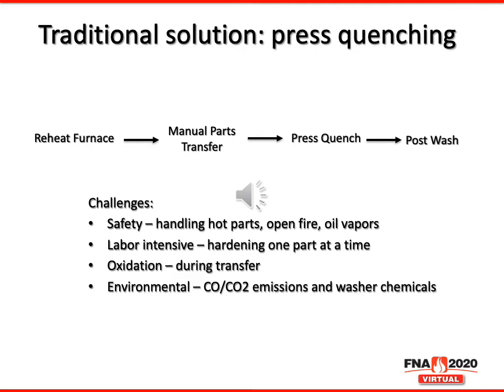Also, each piece is exposed to the ambient environment, which means it's exposed to oxygen. So there's risk for excessive oxidation to the part during transfer. And it has an environmental effect in that it could be releasing CO or CO2, and all of the parts need to be washed, which involves washer chemicals. There's also some additional items like the number of pieces of equipment that are involved. There's the reheat furnace, the press quench, the washer, and keep in mind that, as I mentioned, in that press quench there is a die that has to be manufactured for each part geometry, maintained, and replaced after a certain number of uses.